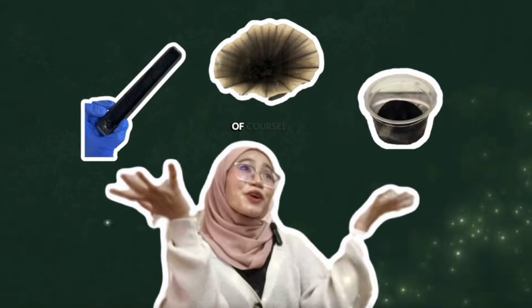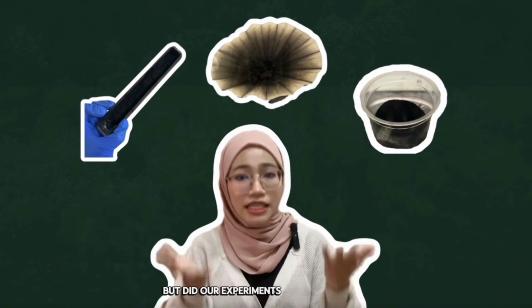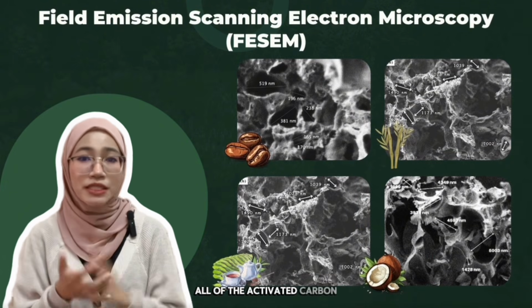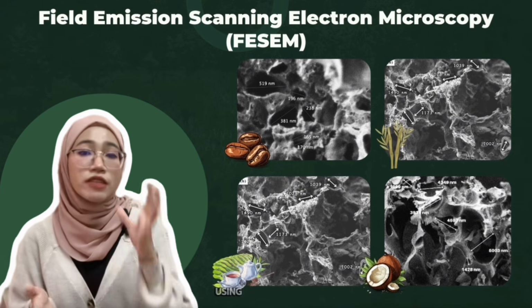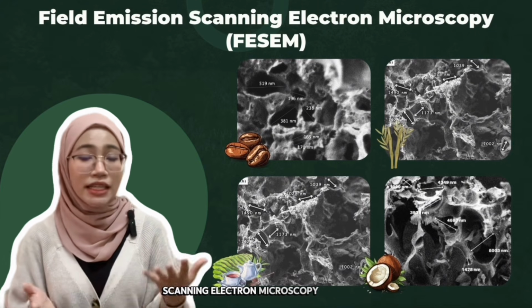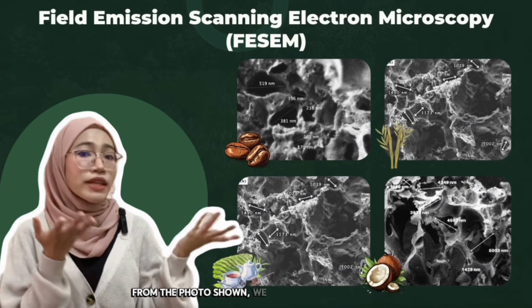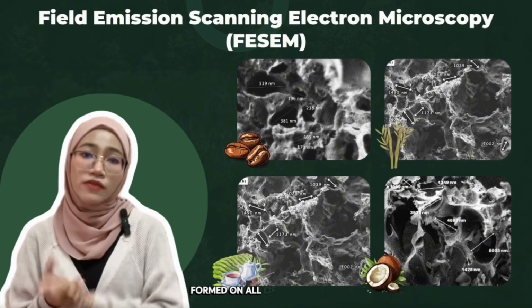So, did all 4 of our biomass waste successfully turn into porous activated carbon? Of course. But did our experiments actually work? Let's check the results. We first tested all of the activated carbon derived from the 4 biomass waste using field emission scanning electron microscopy analysis. From the photos shown, we can clearly see the pores formed on all of the samples.